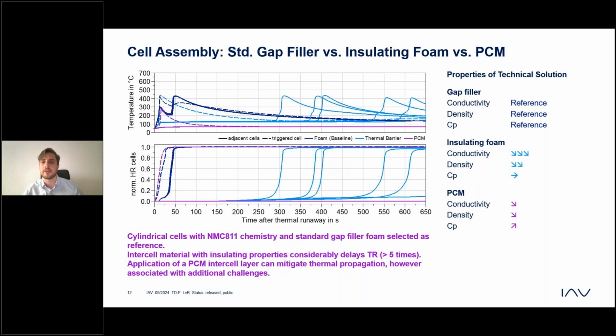As a different material, we have been checking also an insulating foam, which is the blue curves. The insulating foam, compared to our reference gap filler, has a lower conductivity, a lower density, and a similar CP value. We can see that the neighboring cells are getting triggered later, so delayed compared to our reference case. So the insulating foam here works to at least delay the thermal propagation. The same is visible also here in the heat release curves.